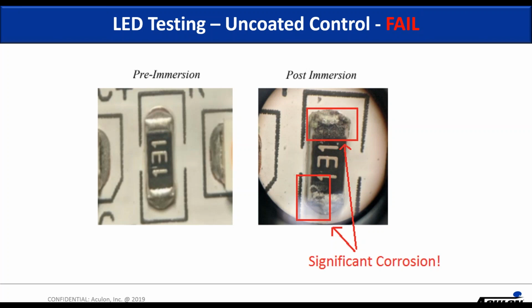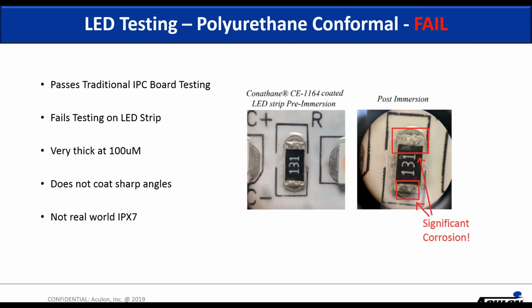So now let's get into the conformal coatings that on the IPC test board passed. So now you start to see some differentiation. They pass the IPC test board, but they fail on the LED strip. These were actually applied at nearly 100 microns in thickness, but these coatings, when you apply them, they simply flow off the edges of the parts. So unless you're applying so much material that you essentially flood all the components above the top level, you're not getting a coating on the sharp angles. And as you can see, the resistor fails at the edges and you have a failed part. So you're not really getting immersion protection.